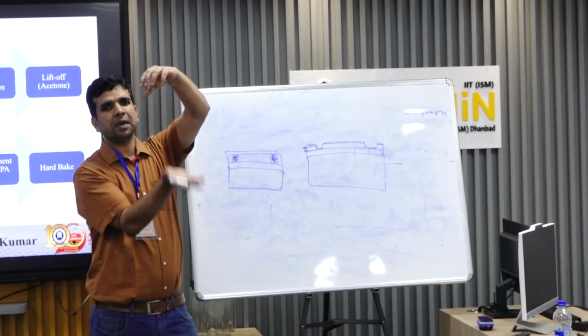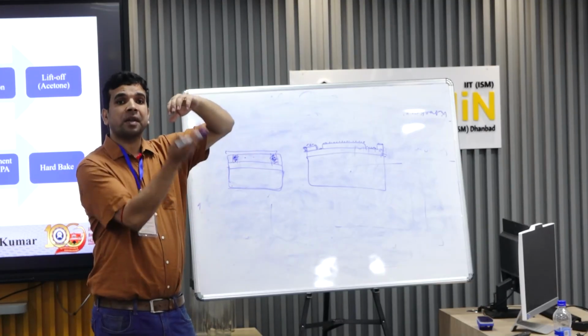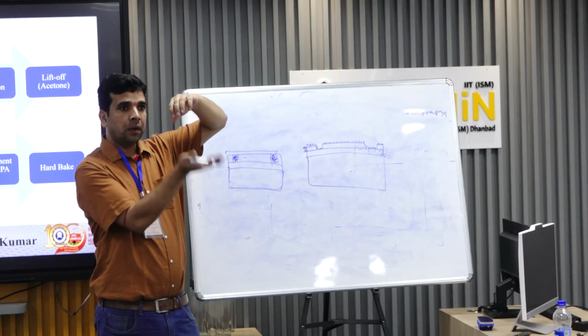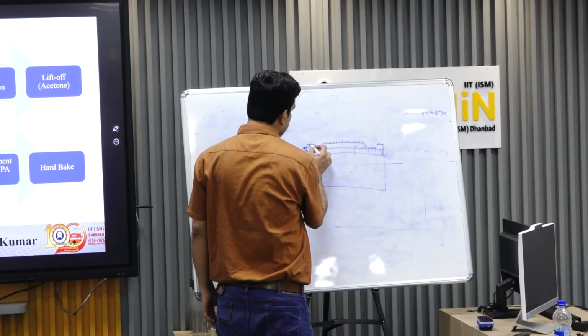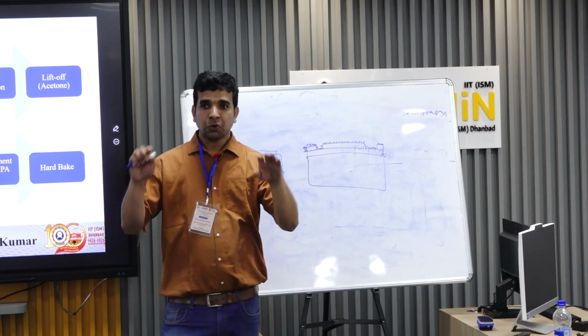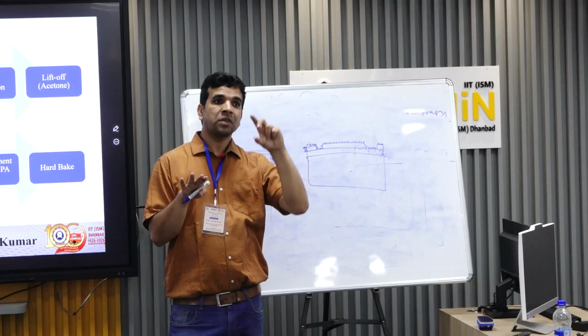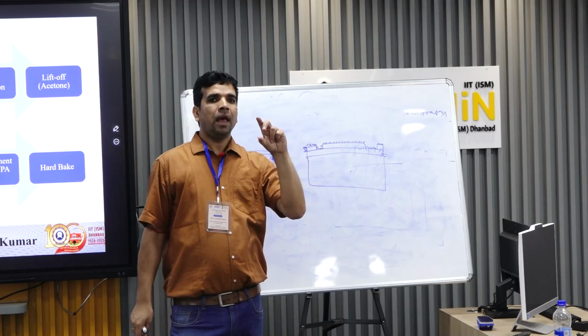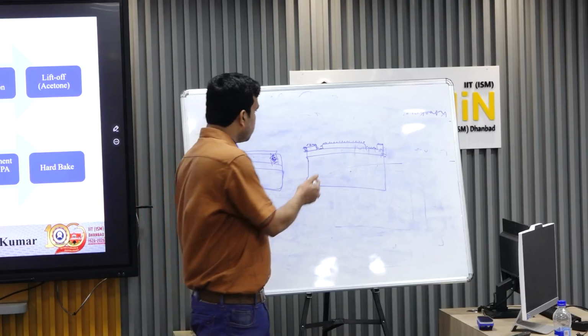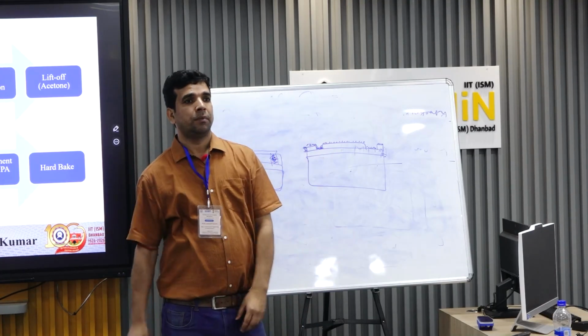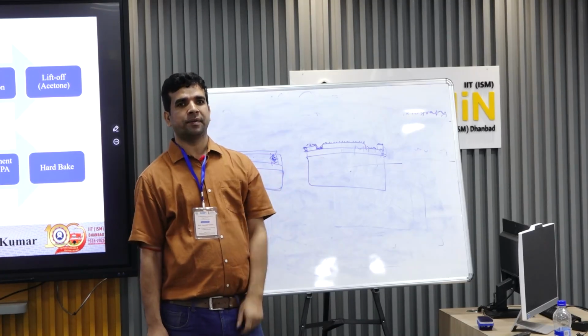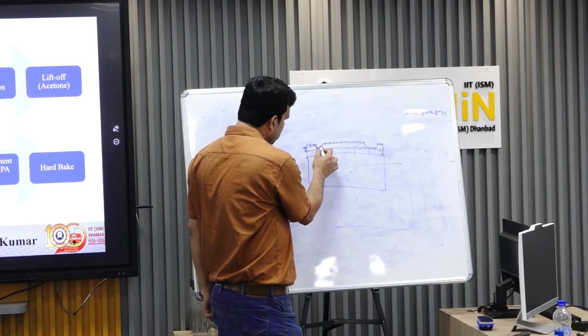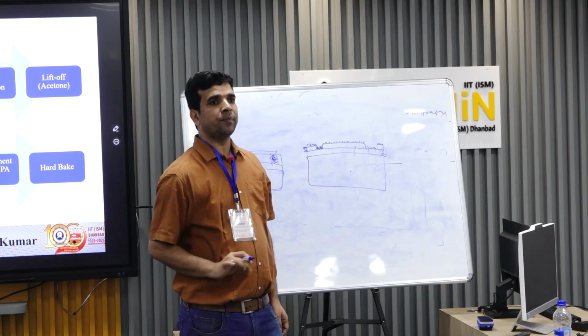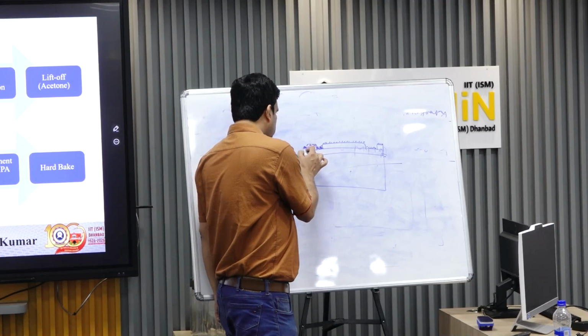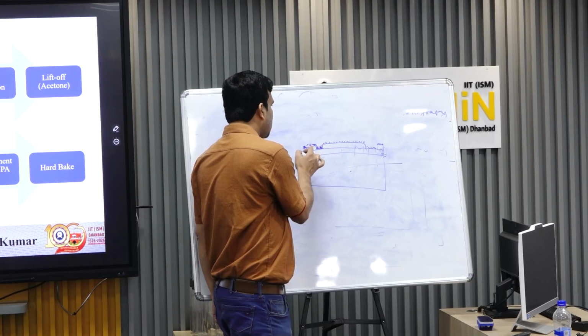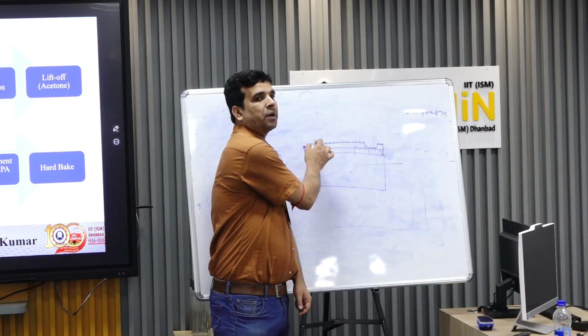Because you have put it and metal is getting deposited. If you deposit for more time, then again this trench will get filled and this can get connected with this. So there should be a proper trade-off between your resist thickness and deposition time. And deposition time you cannot compromise much, because you need a certain thickness of metal here also. Your contact has a certain thickness that you want. So if you want this certain thickness here, then you have to deposit for a certain time, but that should avoid overlap with this. So this resist thickness has to be significantly larger than the thickness you want here.